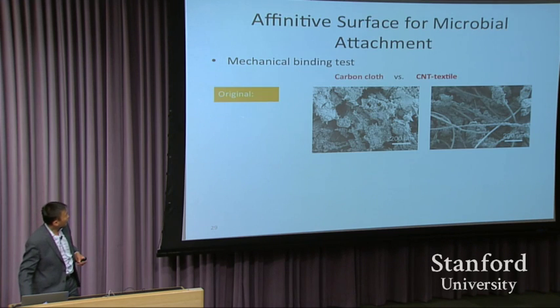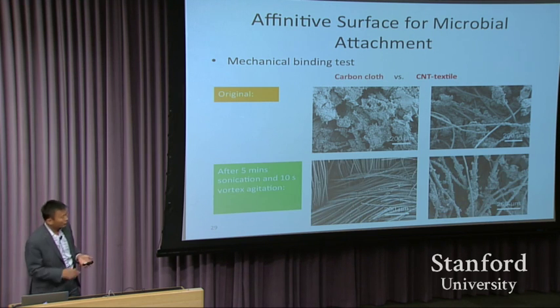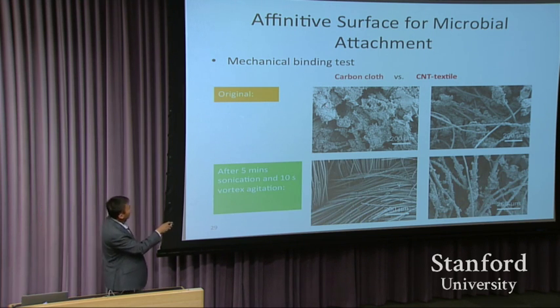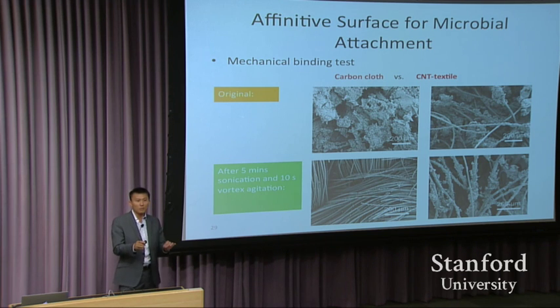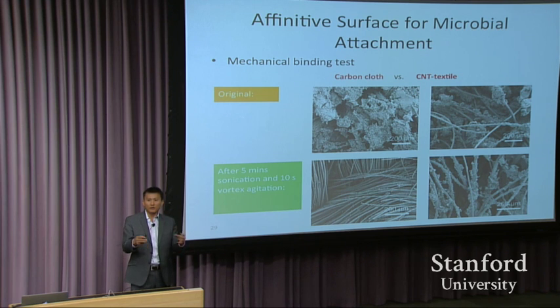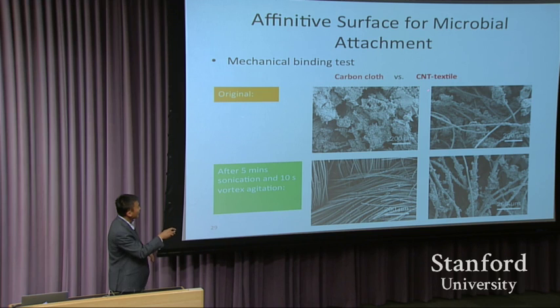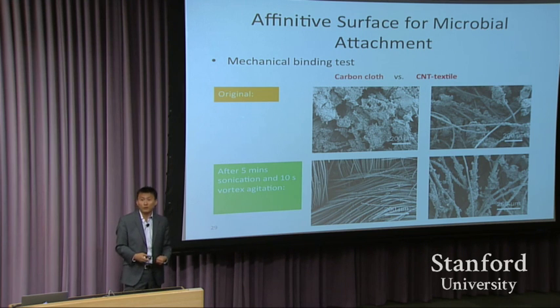If you compare these two, this is the testing. Initially, you grow these microbes onto the carbon cloth. This is carbon nanotube textile. And you do a little bit of sonication, right? Sonication means you try to knock away the stuff stuck onto something, using sonication power to do that. And the CNT, carbon nanotube textile right here, these microbes still stick very well after sonication, but